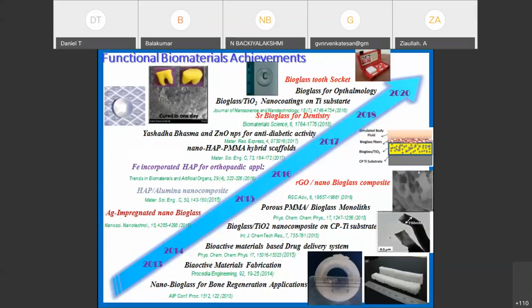So in our lab, we started this work almost in 2011, and we worked with bioactive glass, and then we synthesized this material. Then we moved on to design and fabricate the scaffold. Then we combined it with metal oxide and PMMA and rGO to increase the mechanical property and for coating application. We also incorporated antibacterial silver to improve the antibacterial effect. Then we worked in parallel with HAP and iron oxide, and also we combined it with Siddha material. As of now, for the past 3 years, we are working towards application, product for application.